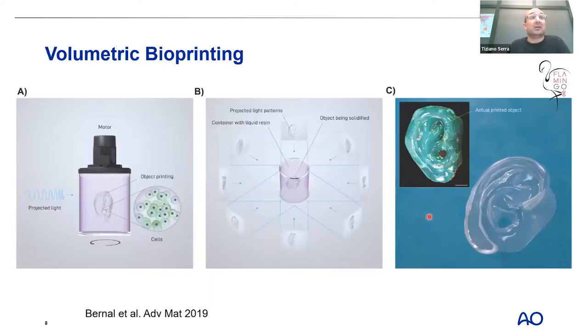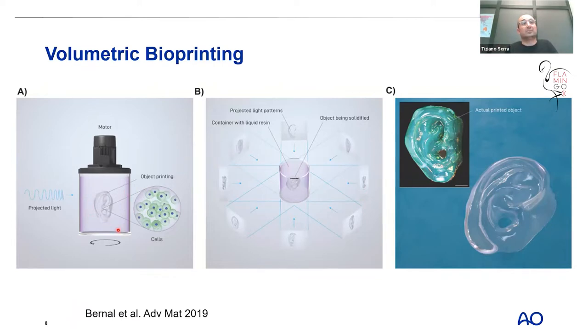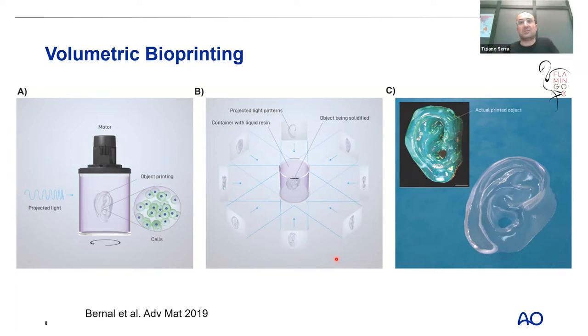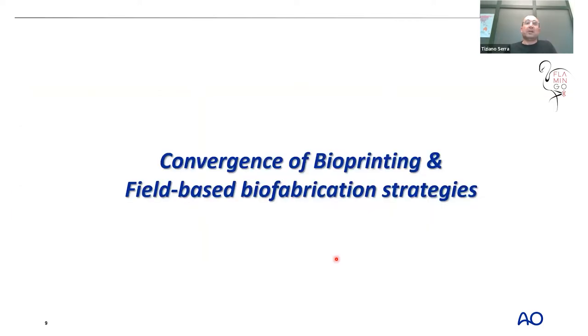Another very interesting technology with a bright future is volumetric bioprinting — a rotating system with a liquid hydrogel precursor that can be cross-linked by light through a mirror system, like optical tomography. This allows generation and cross-linking of highly cellularized constructs in a few seconds at very large scale. I also want to show the convergence of bioprinting and biofabrication with field-based biofabrication strategies enabled by extrinsic fields like magnetic or light fields.